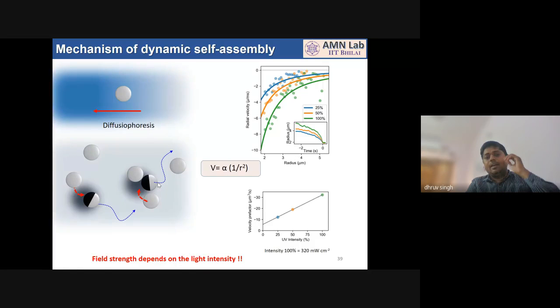Here, the important thing is this whole activity is driven by light. So by controlling the intensity of light, we can control the interaction strength between this nanomotor and the passive particles. Because we are dynamically controlling this interaction strength with the intensity of light, this dynamic control over the interaction strength can be used to tune the size of the structures.